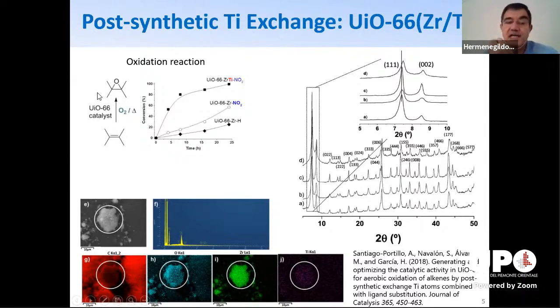And we use it for a reaction that was not Lewis acidity, just oxidation. And what we observe is that compared to the one that contains only zirconium, if you have the 2 metals, zirconium and titanium, then the activity increases. But now moving further, we can also play with the ligand. And if in the ligand we introduce some nitro group, then the electronic positive charge on the titanium atom is even higher, and then you have higher activity. Of course, I am not going to comment in detail, but we have all the characterization of these materials.